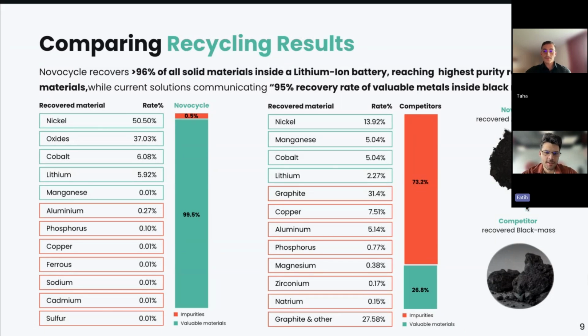Okay, thank you very much. So in the next few slides, we'll compare a few of the results that we can show at this moment. On this slide, we see on the left side the material composition of our recovered cathode materials. And as you can see, the nickel, cobalt, lithium, manganese are recovered in oxide composition. So we don't destroy the microstructure or even the composition that much. And the low impurity, which is about 0.5%, consists of phosphor, copper, iron, sodium, and other trace materials. And usually with another short step, we can even increase the purity up to 99.9%. So a lot of those materials can be removed very easily.